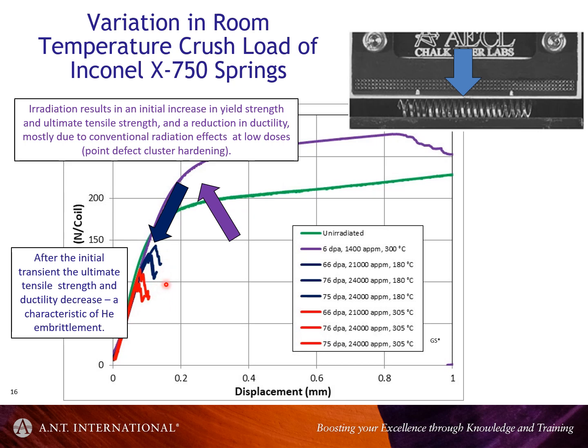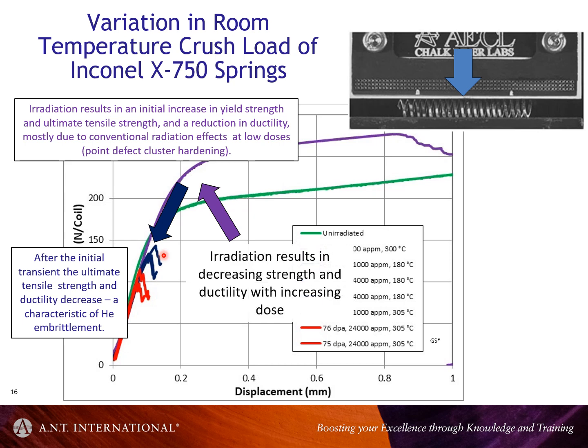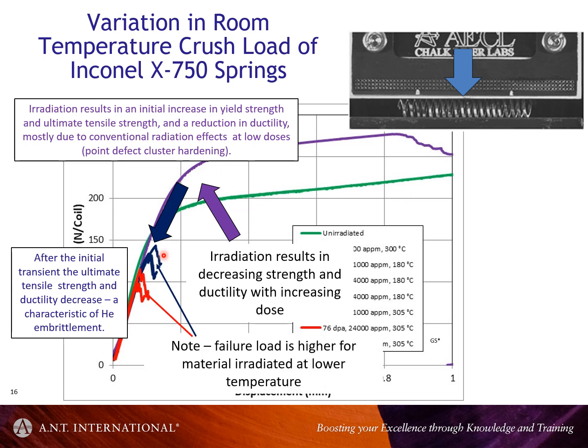The other interesting thing is that there's a temperature difference. I mentioned the flux detectors, which had this apparent temperature dependence of the embrittlement, and it seems that was probably not nitride cracking, but really helium embrittlement. And what you see is that if it's a higher temperature, in the red here, the embrittlement is worse compared to the lower temperature. Irradiation results in decreasing strength and ductility with increasing dose, and once you get past a certain low dose, the degradation is just dropping, as you see here.